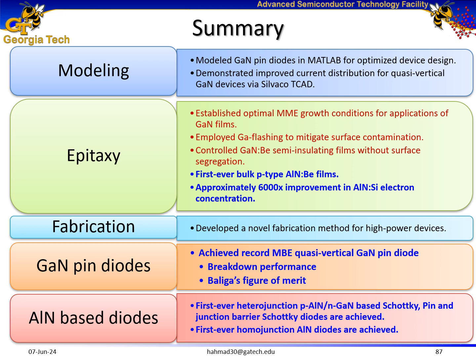To summarize my key results, my scientific contributions include modeling, where I've shown gallium nitride PIN diodes in MATLAB for optimized device design. I've demonstrated improved current distribution for quasi-vertical gallium nitride devices via Silvaco TCAD. From epitaxy point of view, I have established the optimal growth conditions for different device applications. I've shown gallium flashing to mitigate surface contamination. I've achieved controlled beryllium-doped gallium nitride semi-insulating films for different applications. I've achieved the first ever P-type bulk aluminum nitride films.